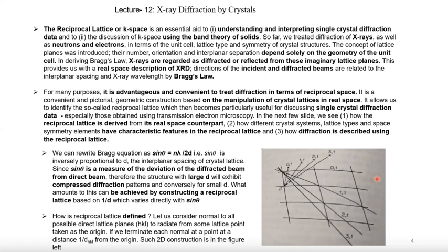Why not single crystals? In powder data, when you get a peak, it is an average of the same family of planes. You get an intensity average of the same family of planes. But for single crystal data, it's not an average. Every Miller index gives a spot, and we have many data points for single crystal to analyze the structure.